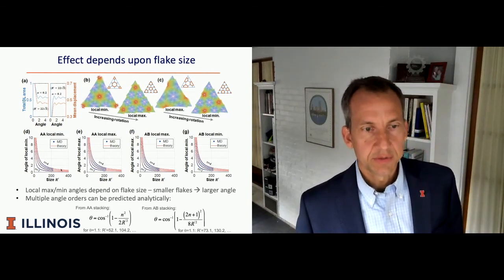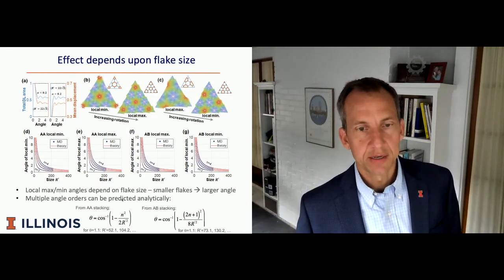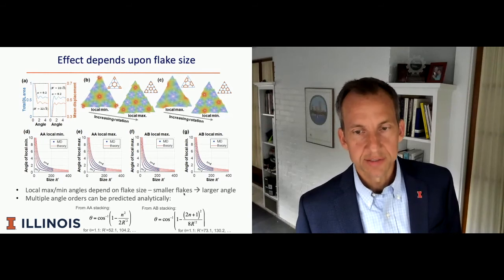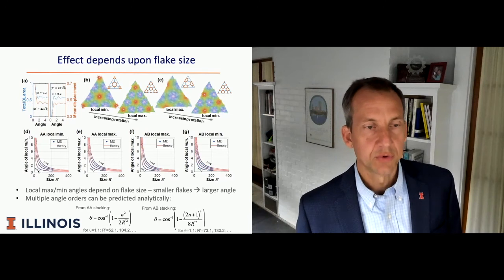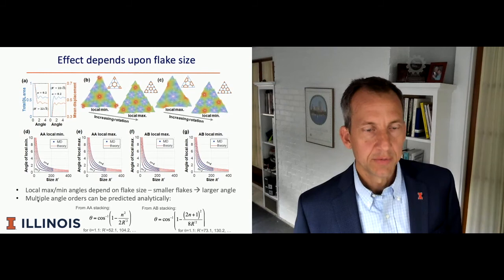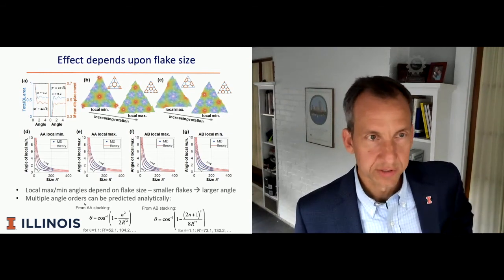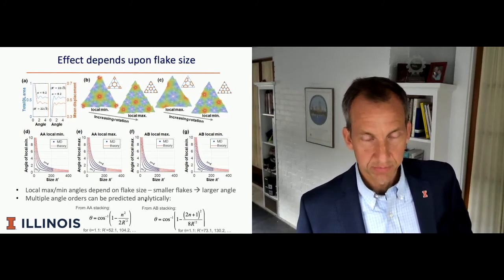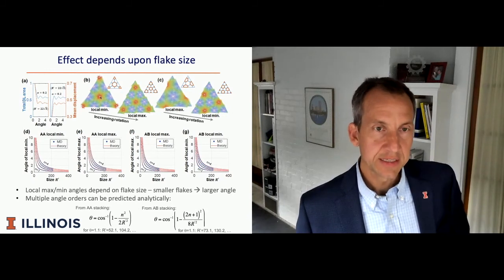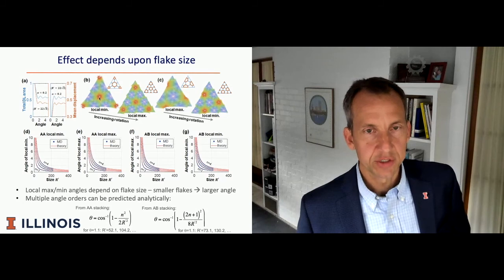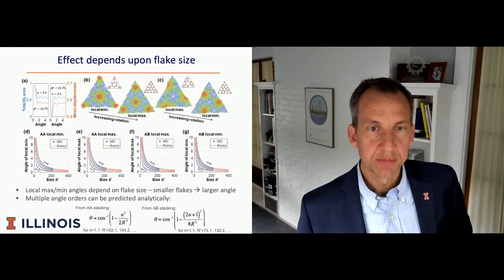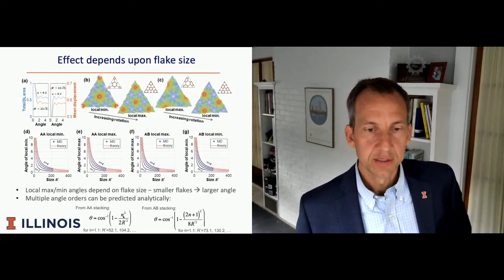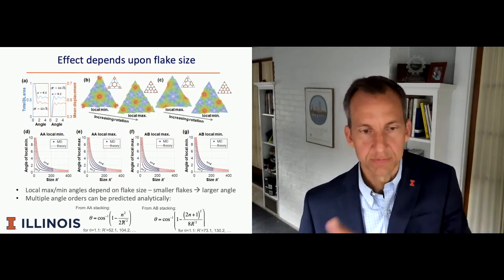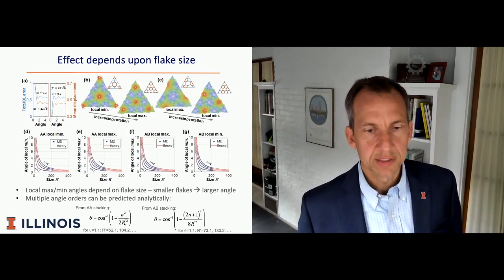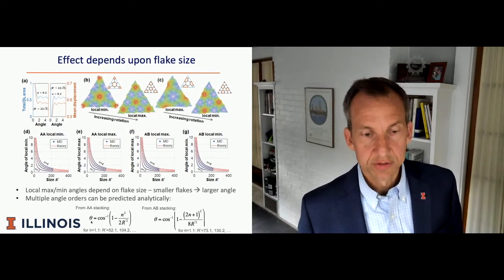Now, as I said, the local maxima and minimum angles depend on the flake size. Smaller flakes have larger angles for their local minima and their local maxima. Indeed, it's possible to predict these multiple angle orders, first, second, third, fourth, and so on, analytically. Without going into the details of the model, the point is that the positioning of the moire spots, and therefore the arrangement of the dislocation network, is quite different in the case of a local minimum than in the case of a local maximum. If we treat n as the order of the first, second, third, fourth minimum, and so on, and r prime as a normalized size of the flake, we can predict the angle for a certain flake size.